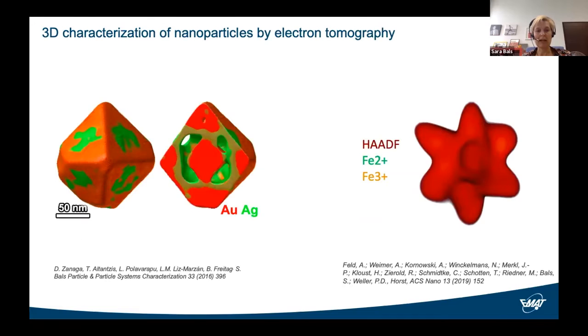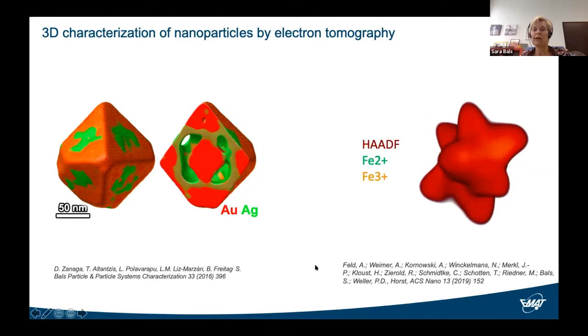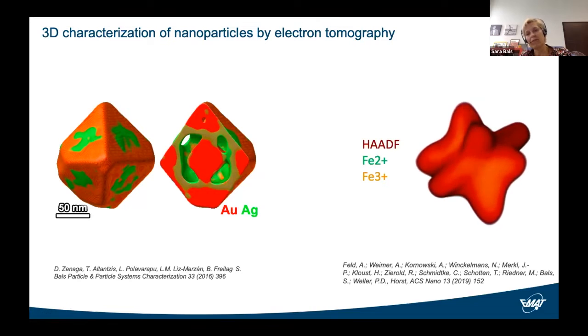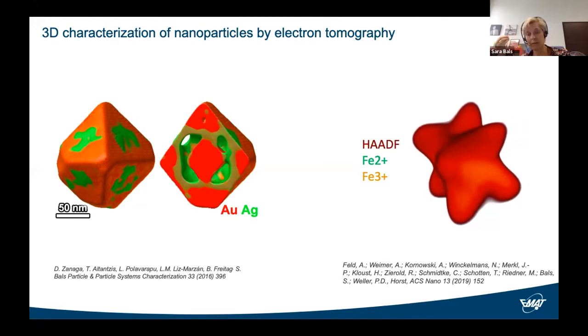So electron tomography is a very good technique to investigate the structure of nanomaterials, but we can also combine the concept of electron tomography, for example, with EDX, which stands for Energy Dispersive X-ray Spectroscopy. And on the left, you can see a three-dimensional reconstruction in which every voxel, so voxel is a three-dimensional pixel, contains the ratio between gold and silver. On the right, we have combined electron energy loss spectroscopy, EELS, with tomography, and this is in fact a four-dimensional data set because every voxel now contains a full EELS spectrum.